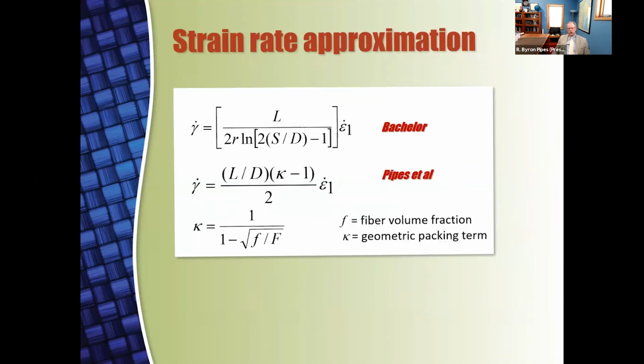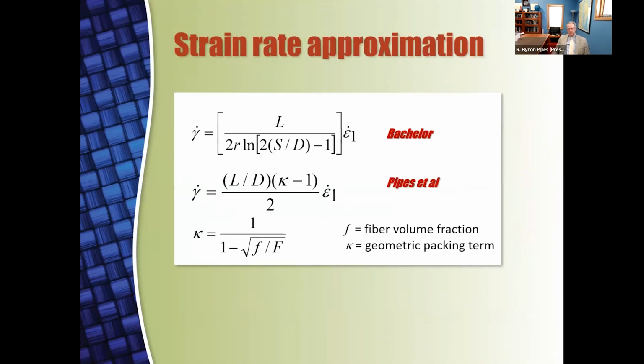And so you can write the polymer strain rate as a function of the extensional strain rate of the composite in terms of the fiber spacing and diameter. The fiber spacing is S, their diameter D, and a term kappa, which relates to the fiber volume fraction.